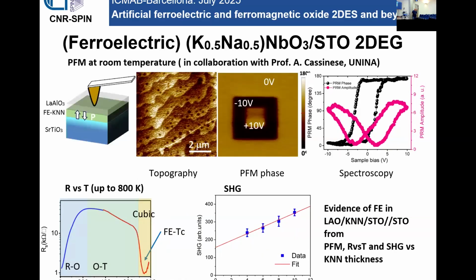And finally, we performed some characterization to understand if the KNN is ferroelectric in the heterostructure. Since in order to get a nice heterostructure, we need a layer of KNN which is maximum 10 unit cells, so it's very thin, we should use techniques which don't have the problem of leakage current, essentially. So one technique is piezo-force microscopy.